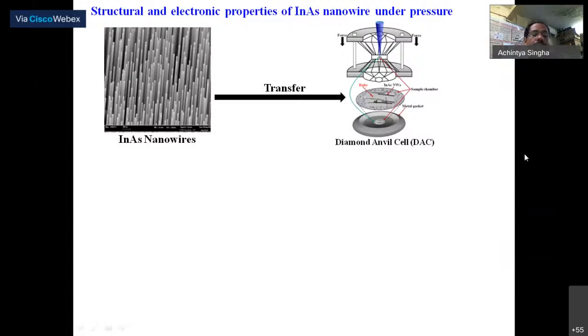Again we did the InAs nanowire high pressure experiment. We use a diamond anvil cell, DAC, and we place the nanowire at the gap between the two diamonds, as you can see in the right side picture. The tips of the diamonds are facing each other, and if you apply a little force between the diamonds, as pressure depends on the area, a huge pressure is created within the sample. By this experiment we can apply pressure up to 60 GPa.